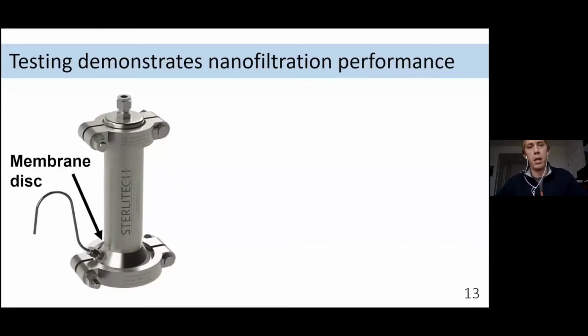So just a bit on the actual filtration testing. The way we do this is pretty simple. We're able to mobilize these membranes in these pressure cells that we can buy off the shelf. In the bottom of this cell here, as you can see, the test solution is then placed in that pressure cell chamber above the membrane itself.